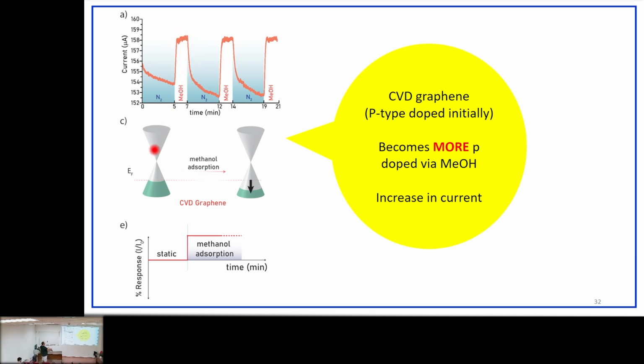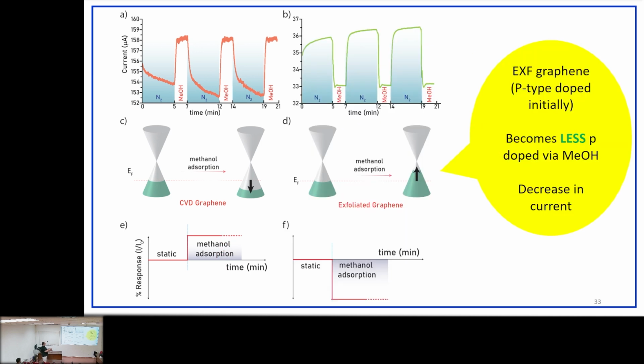In this slide, whenever you send your methanol molecules, you obtained an increase in the base current. Why? In the beginning, CVD graphene was p-type doped like this, and after charge transfer, it became more p-type. Becoming more p-type means that around the Fermi level you have more electronic carriers, and in the end you have an increase.